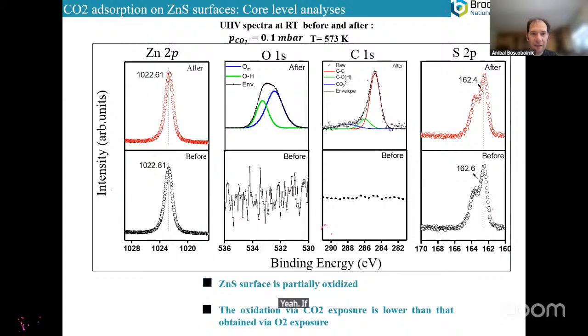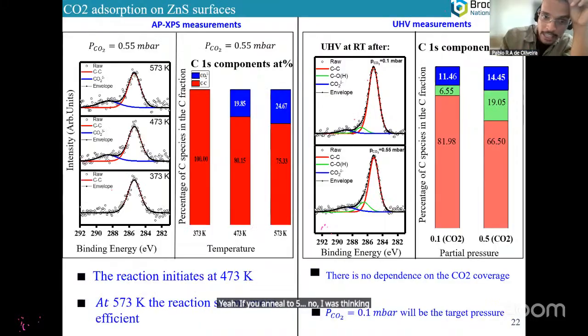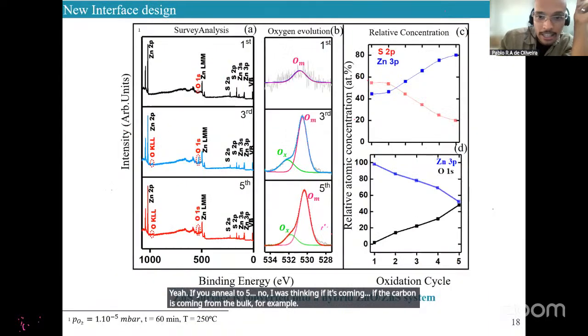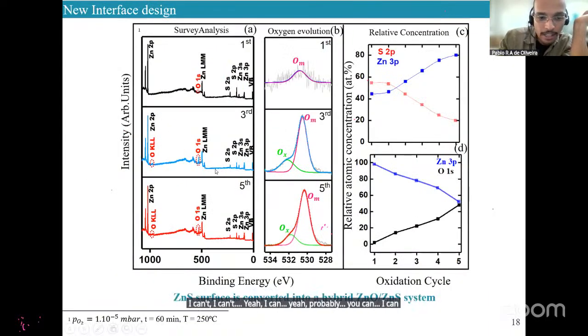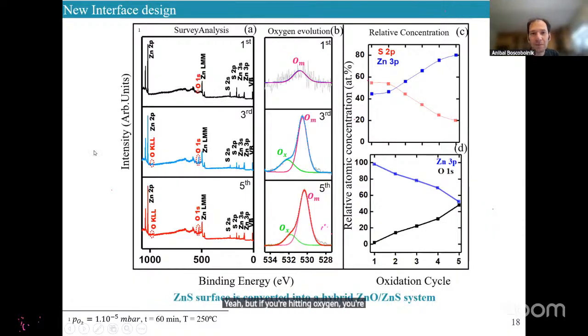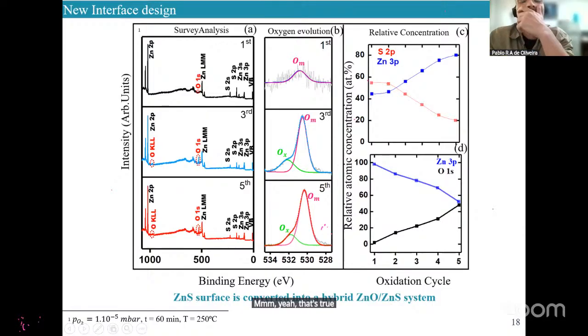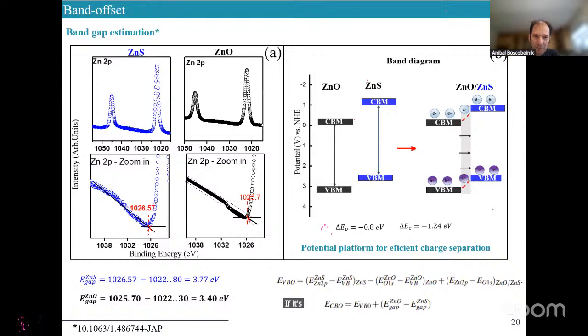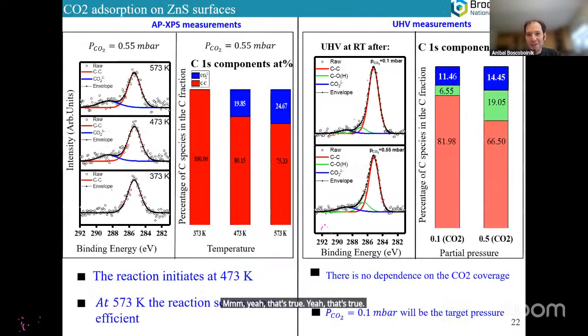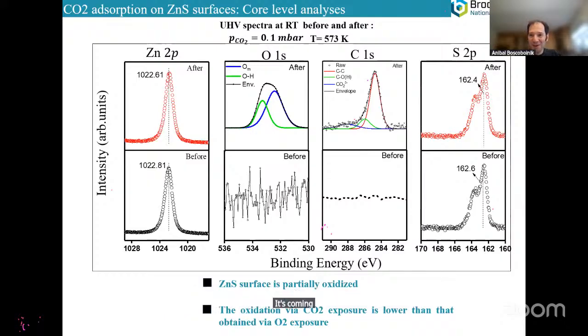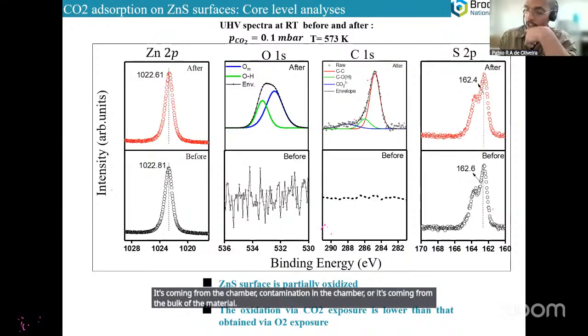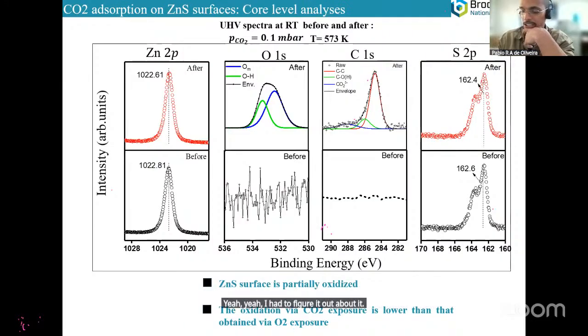I was thinking if the carbon is coming from the bulk, for example. Yeah, probably you can. I can show you this data. For the oxidation, I heated up the system at 10 to the -5 millibar of oxygen, so there's no carbon peak. Yeah, but if you heat in oxygen, you're burning the carbon. Yeah, that's true. If it's coming from one source, it's either coming from the bottom or from the top, right? It's either contamination in the chamber, or it's coming from the bulk of the material. I have to figure it out. I don't know.